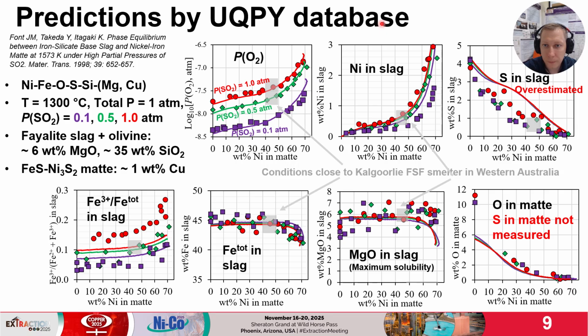And the accuracy of model predictions is within 0.2%. Please note the scale. It's quite small. The solubility of sulfur in slag is likely overestimated by the current model. The iron 3 plus versus total iron in slag is significant and reasonably well predicted by the model. Higher values for PSO2 equal 1 atmosphere is likely an experimental issue.